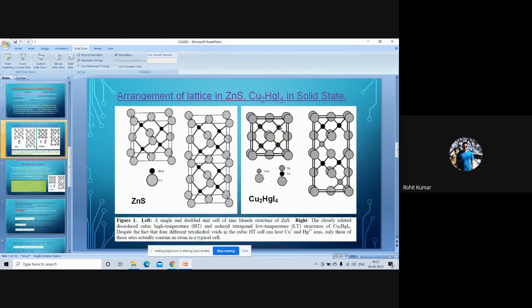So here we can see that not all the tetrahedral sites are occupied. Basically, it's the same as zinc sulfide, but in zinc sulfide, zinc occupies alternate tetrahedral voids. But in this case, not all the alternate tetrahedral voids are occupied. Only two copper and one mercury occupy tetrahedral voids. This phase transition is accompanied by a color change from brick red to red brown, and a marked increase in electrical conductivity is seen, and the band gap decreases from 2.1 to 1.9 with the change in structure. In this high temperature phase, the unit cell is cubic. We can see here.